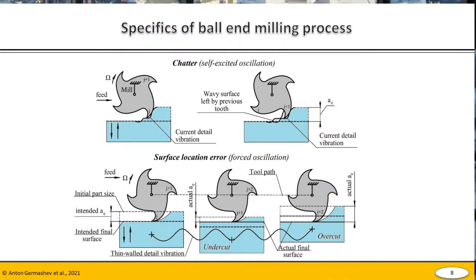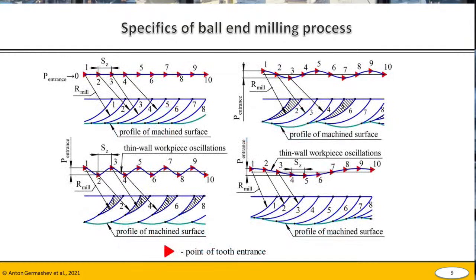So basically, our results show that the main influence on the surface formation and the behavior of the milling process is the position of the tool and the position of the part when we are discussing the milling of thin wall components and high-speed machining. So it is very important, if you're talking about thin wall details, the position of the part at each consecutive cutting process. The next slide, please. So we're able to observe here that, depending on the position of the part at the moment of each consecutive tooth entrance, this process determines the quality of the surface finish. The next slide, please.